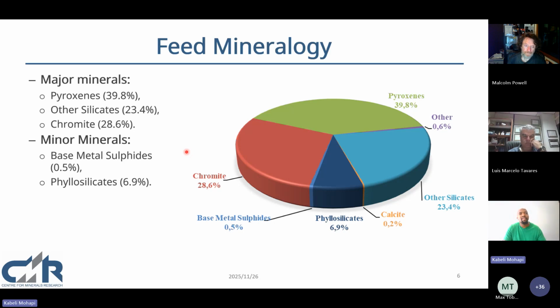There's a minor constituent of base metal sulfides that were found in the bulk mineralogy, and these are of importance in our research as they could be of economic importance. However, there was a concerning amount of phyllosilicates at 6.9%, as these are components that could lead to a high amount of slimes, and there was also talc within these phyllosilicates which could contaminate our concentrate, as talc is naturally floatable.